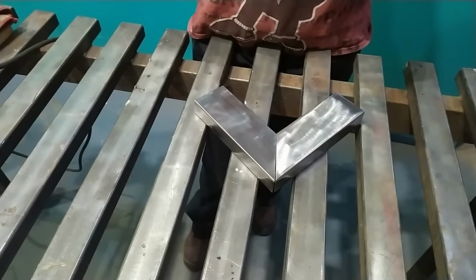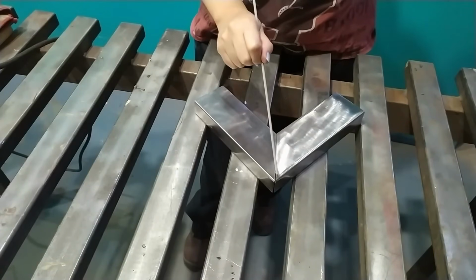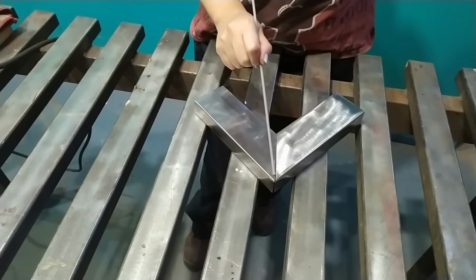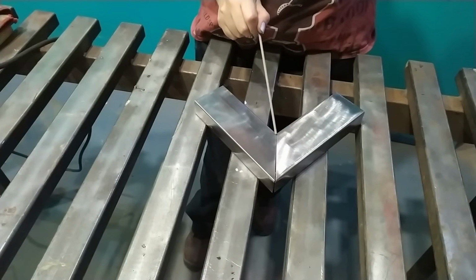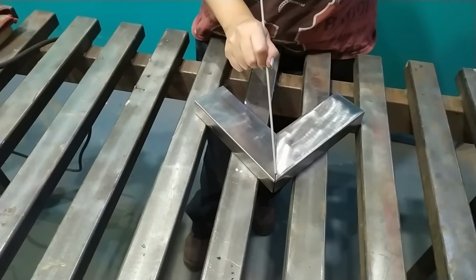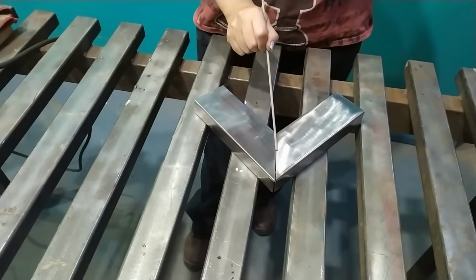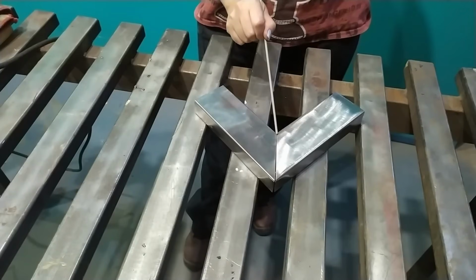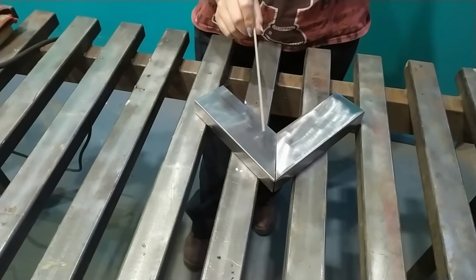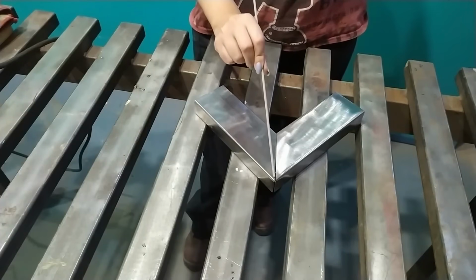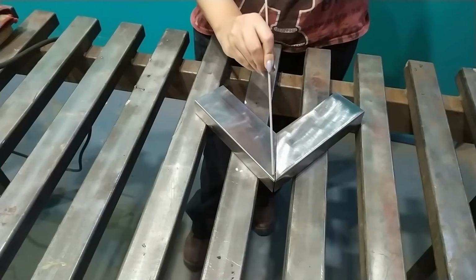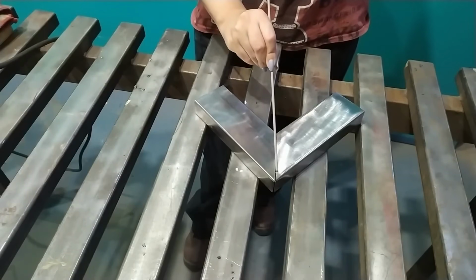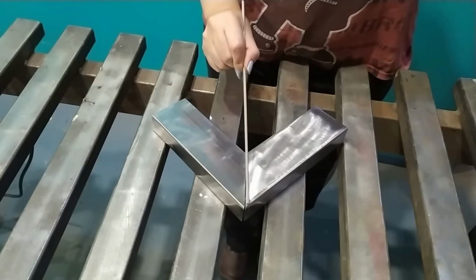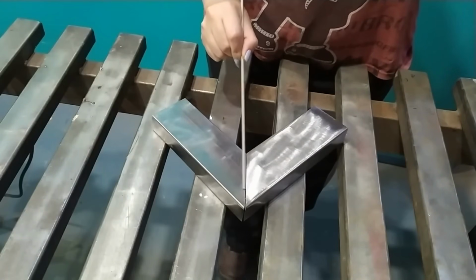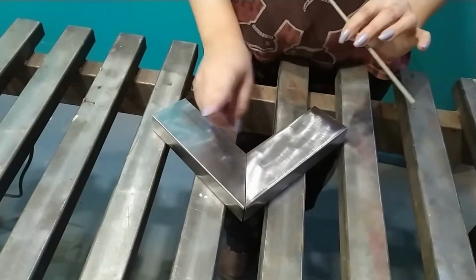To weld this profile, if we have the 2.5 electrode, we will do it at 50 amps with tack welds. Now, if we have the 2 millimeter electrode like I do, we will do it with a continuous bead. We are going to tack both ends. Once we have it tacked, we can weld continuously. The movement we are going to make is none. What we're going to do is drag the electrode backwards, following the joint line at a fairly fast speed. In this type of welding, you don't need to make any side-to-side movements. You just need to slide the electrode backwards.